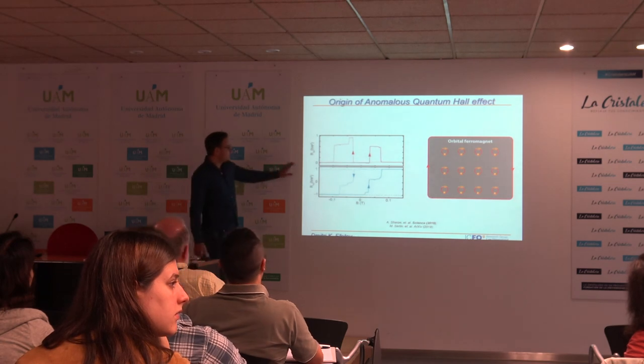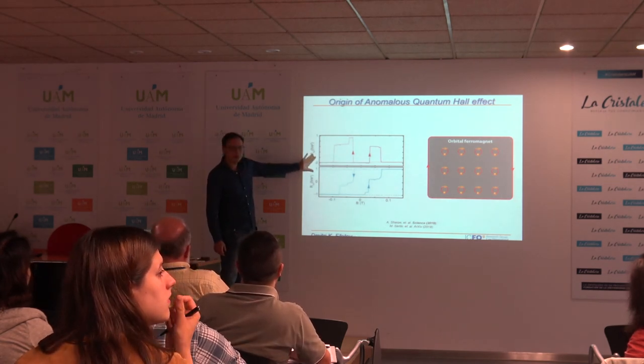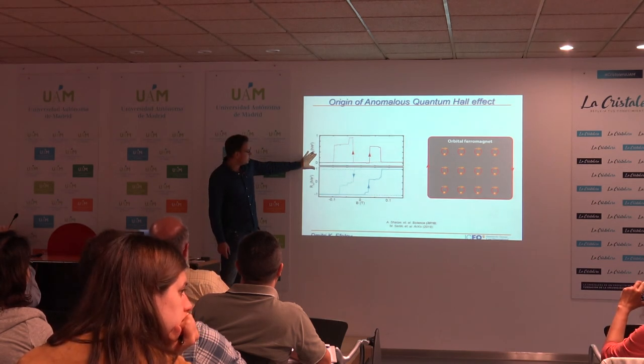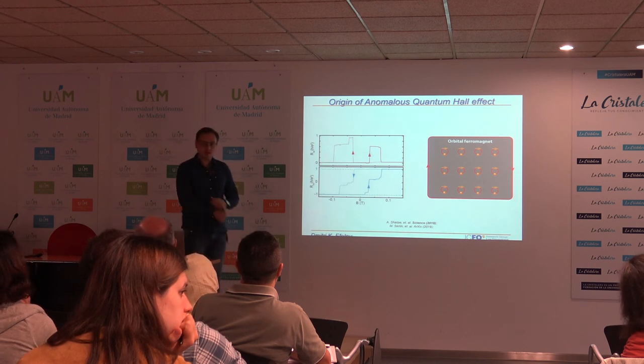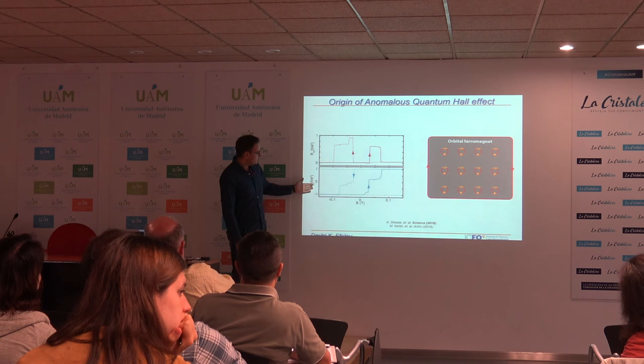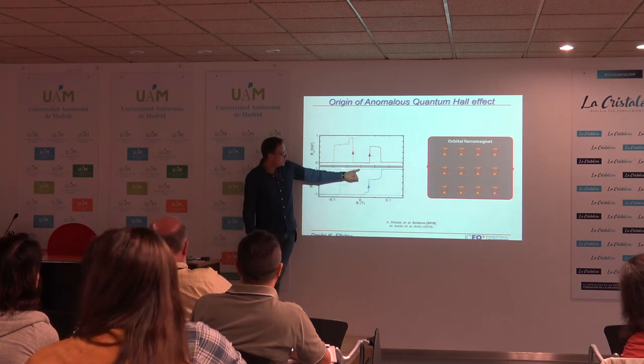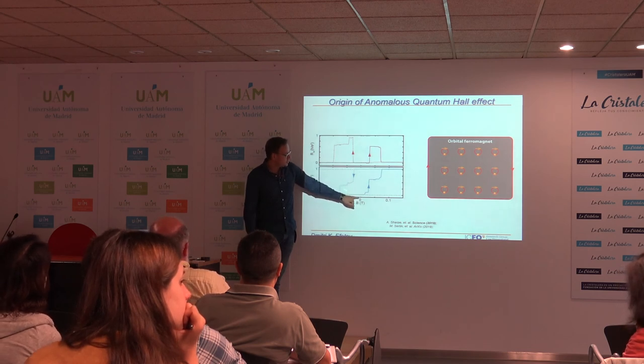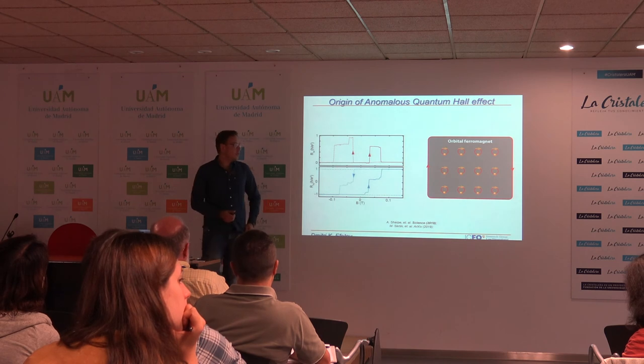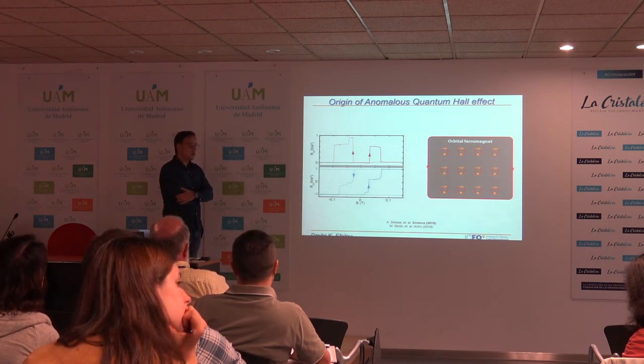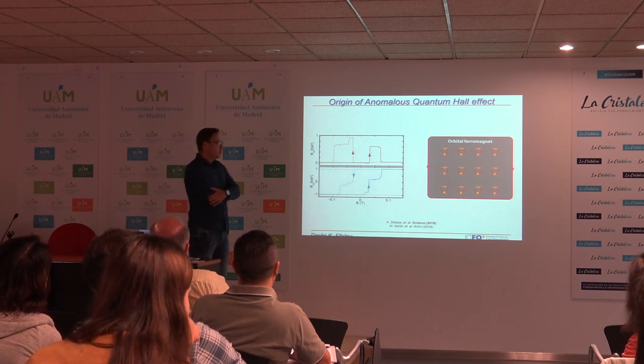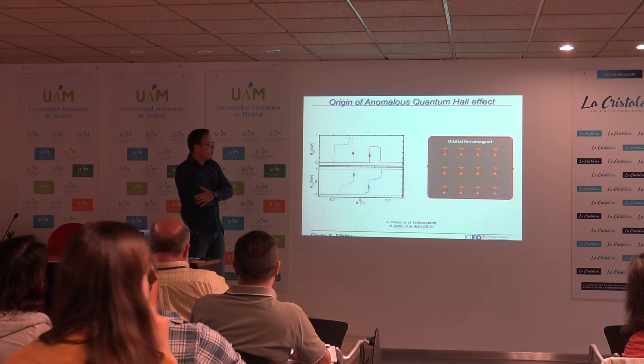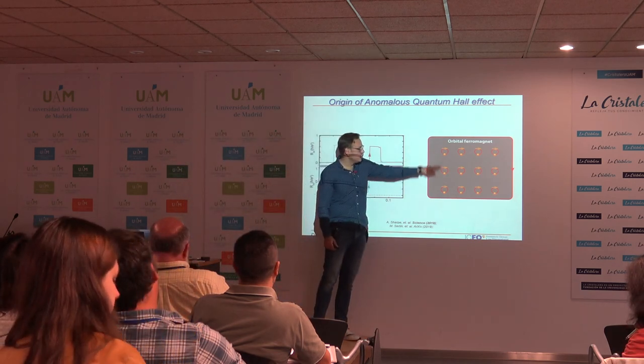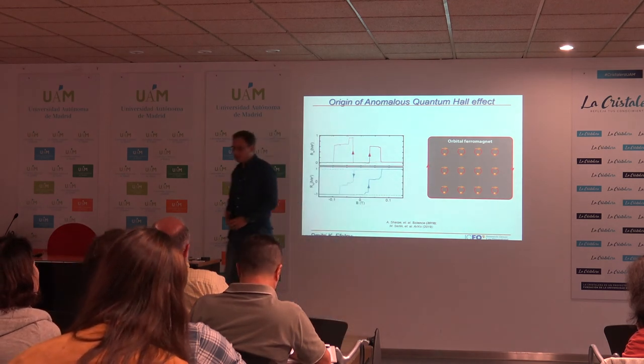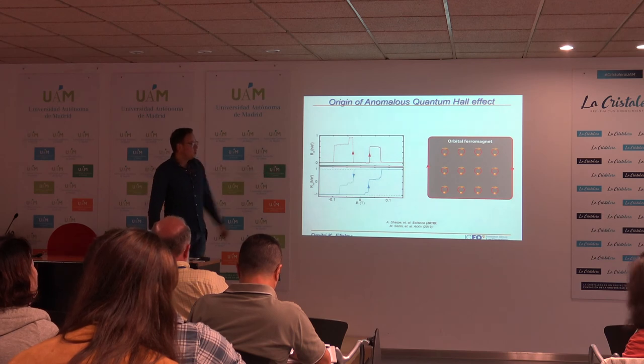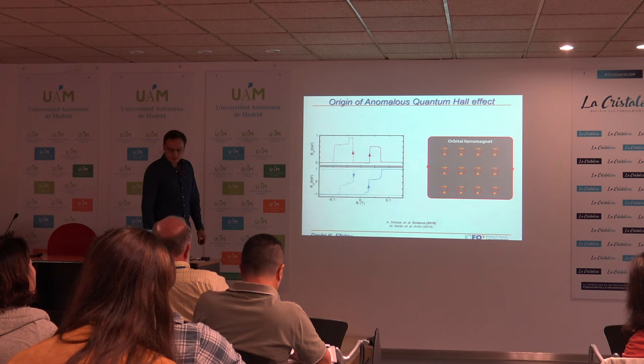This is, for example, a picture from the UC Santa Barbara group. Indeed, they have measured this type of effect in twisted bilayer graphene. Again, they measure Rxy as a function of magnetic field, and they see really perfect quantization of plus one and minus one at around zero magnetic field. The ongoing explanation right now is that presumably it's an orbital ferromagnetism developing in the twisted bilayer graphene. The idea is that you have these current loops forming, presumably because valley degeneracy is broken, and then you develop this orbital ferromagnetic phase based on this.